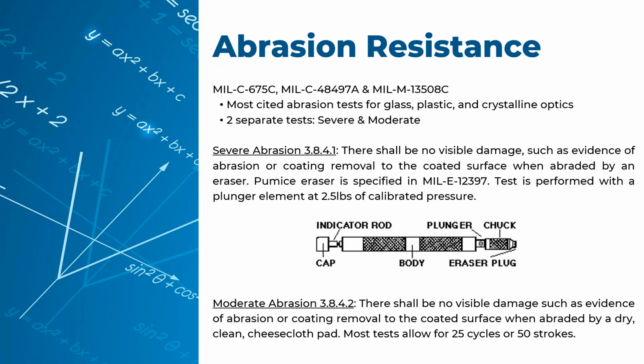If I stroke this coated side 50 times with this cheesecloth, am I going to induce stress on the film? Is the film going to be cloudy? Am I going to start to break the film up? Am I going to start showing scratches in the mirror where, if I keep abrading, I can pull the film away from the coated substrate? So again, this is a moderate abrasion test, almost always used in polymeric optics and a less challenging environment. Anything used in a laboratory, anything used in a controlled environment that isn't going to be handled a lot or cleaned regularly is probably fine under moderate abrasion.